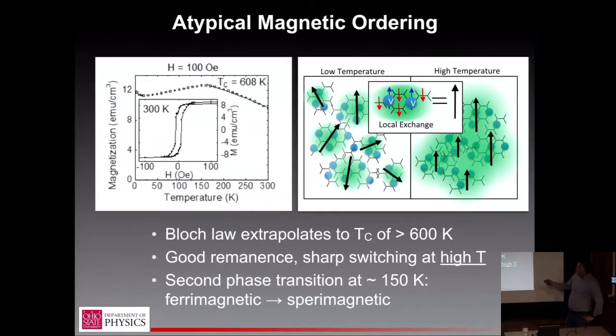But what we think is happening is that this is also a reasonably good organic semiconductor. So mobility is maybe somewhere between 0.1 and 1, I think, for typical films. So as we heat it up, we start thermally activating more and more carriers. And as those carriers can move around over larger distances, they can bridge some of these gaps and drive global uniform magnetic ordering in the film. So this is what you're seeing here, this rise. As you go from low temperature to high temperature, it gets better ordered, which is weird.